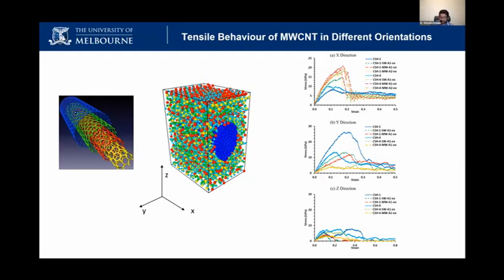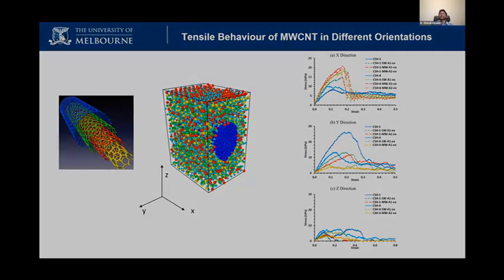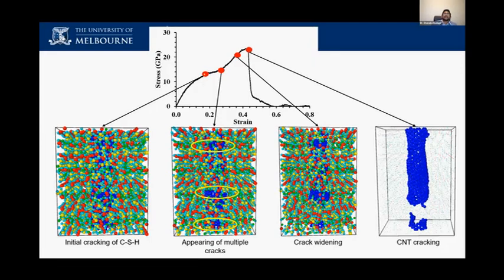Kanishka did a very good analysis. Actually, we will publish this work very soon. This is how we understand the behavior: what causes the initial cracking or the yielding, then the crack progress, and then the sudden drop is due to the failure of the carbon nanotube. We can observe and explain the mechanism happening here, depending on the type of carbon nanotube and the direction of the CSH chains. We can explore those things using molecular dynamics.